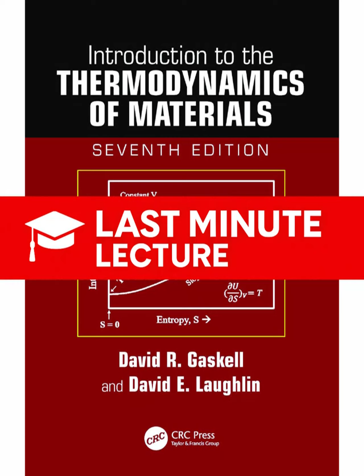That extra magnetic disorder gives its G curve a steeper negative slope, allowing it to drop below the alpha phase's curve at high temperature. It shows that phase stability is this delicate balance of all forms of disorder: vibrational, configurational, and, in this case, spin. That puts the whole G versus T discussion in a totally new light.